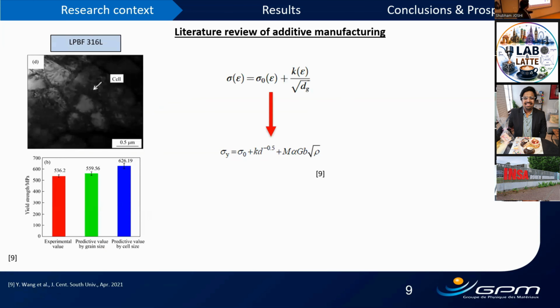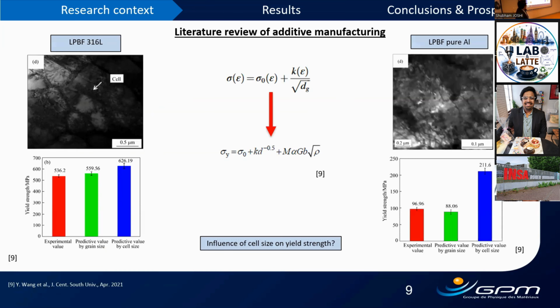This is an interesting piece of research. What they did is they tried to modify the Hall-Petch relationship and use cell size to predict the yield strength of LPBF 316L, and then compared it with the prediction from grain size and the experimental value. And it seems that it's a good match. But when the researchers tried to reproduce this with LPBF pure aluminium, we see that with cell size, it's a clear overshoot. So now, again, we have the same question. Is it process based? Is it material based? So there's still an open question.